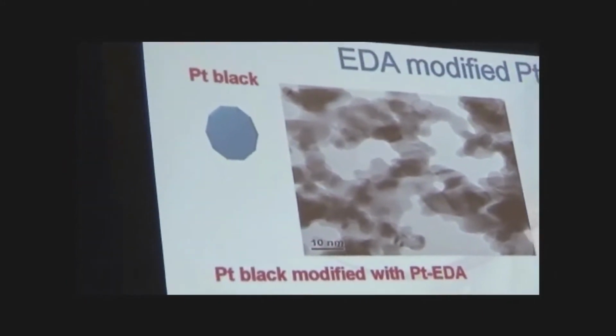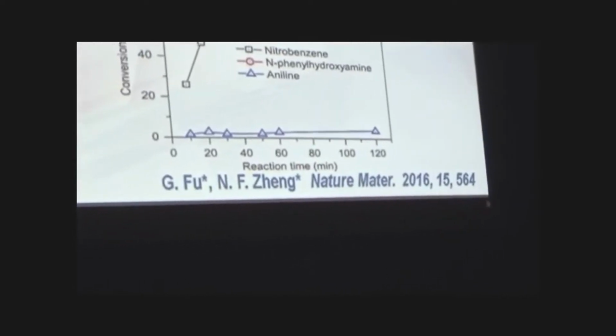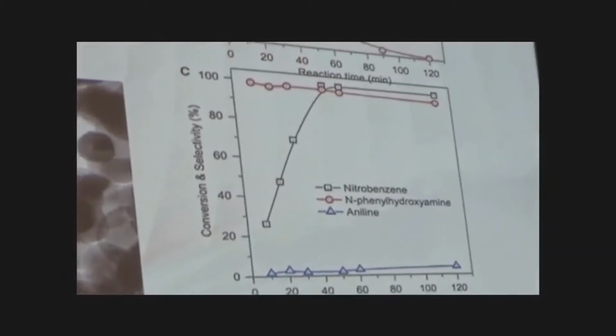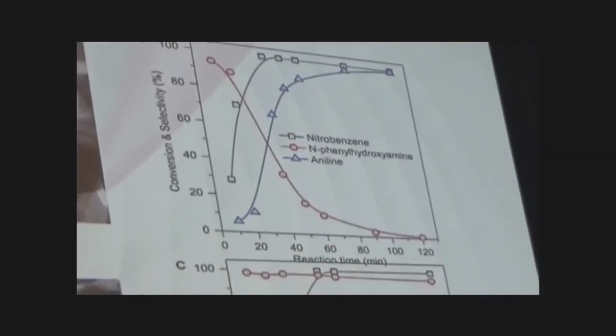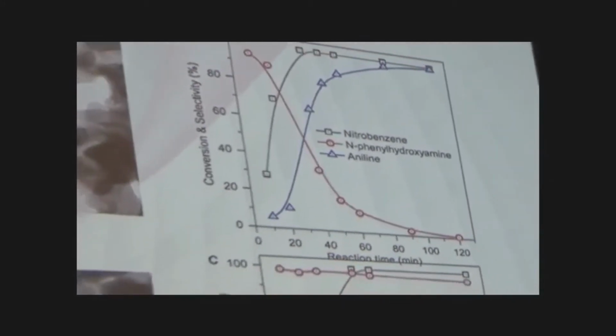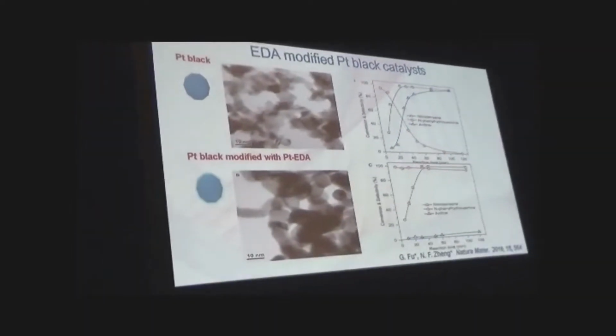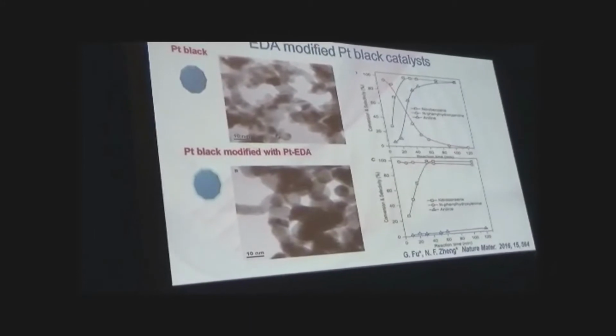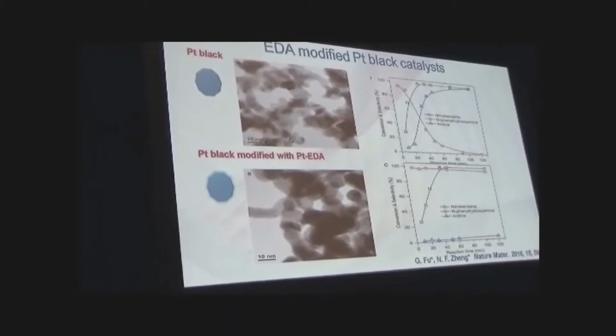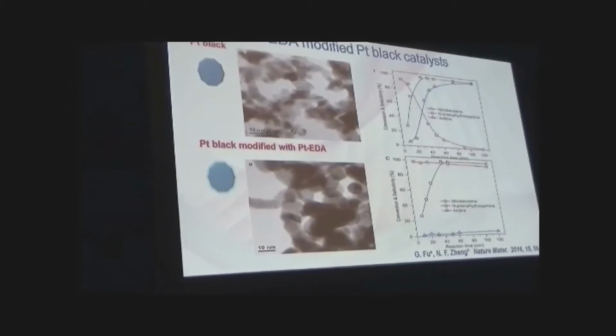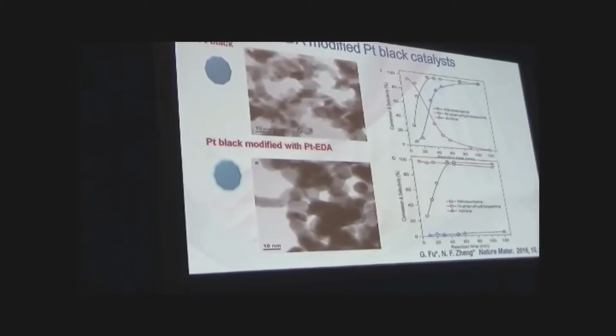Look, here is Pt black. You know Pt black has selectivity towards the aniline. Here, instead of plain Pt black, we use a modified Pt black. How to do this? We start from Pt black with the Pt ethylenediamine precursor. We use in situ reduction to generate many Pt atoms on the surface, with the ethylenediamine absorbed on the surface. In this case, you can see that we can also get very high selectivity toward hydroxylamine. So it's an electronic effect.